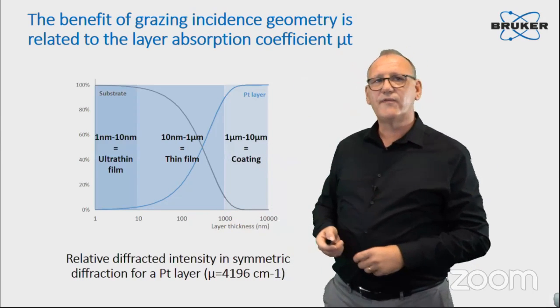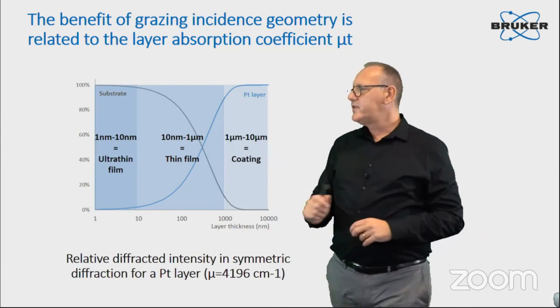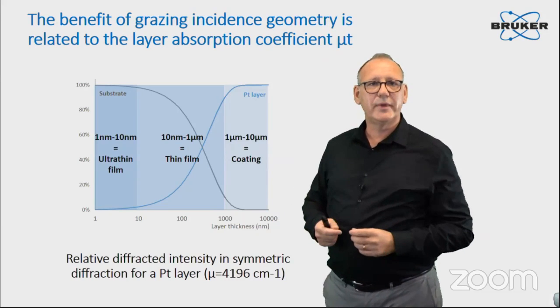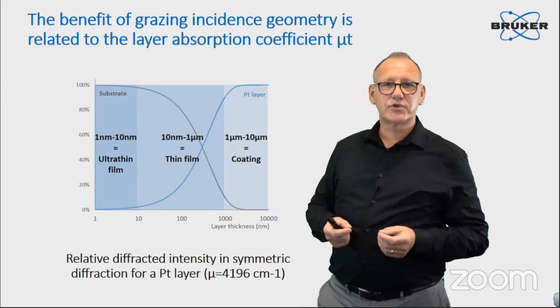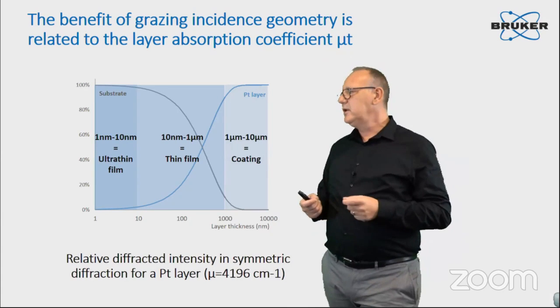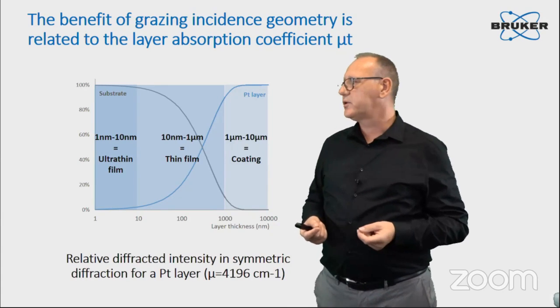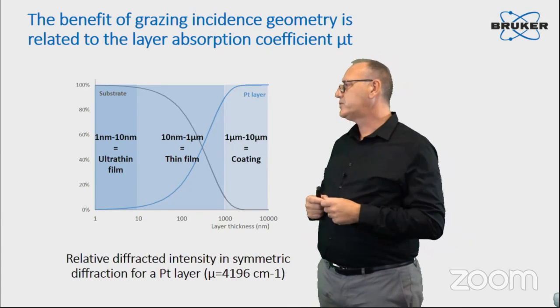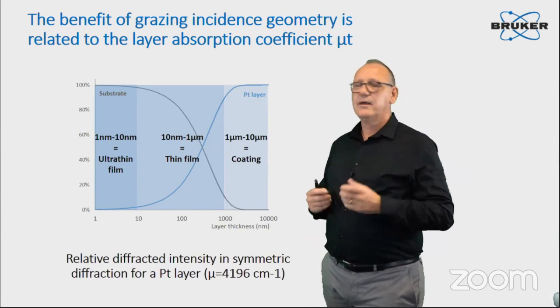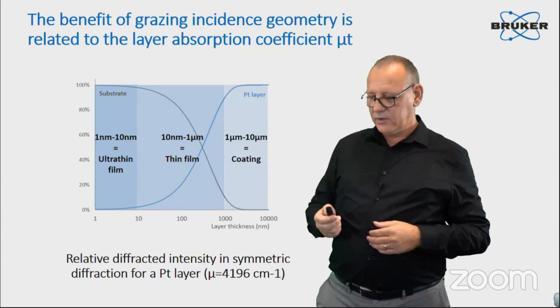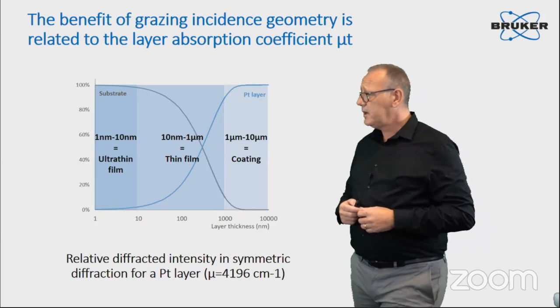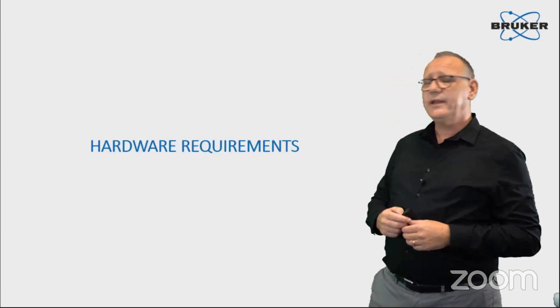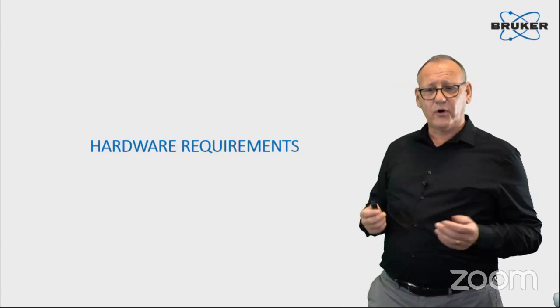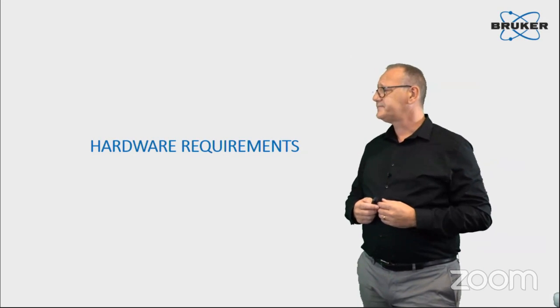If you now go for even thinner layers, from 1 to 10 nanometer, then the layer contribution is almost invisible. You are below 1/100 or 1/1,000th compared to the substrate signal. And there's no way out other than doing a GID measurement. So let's see what we need to set up to perform grazing incidence diffraction.